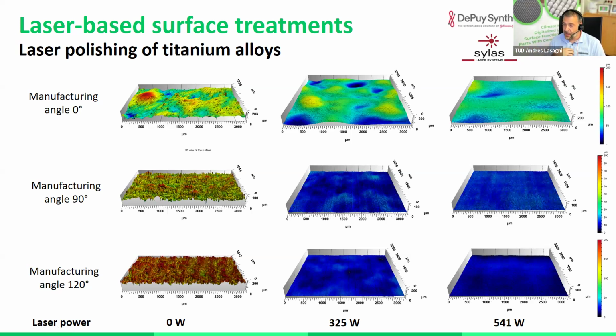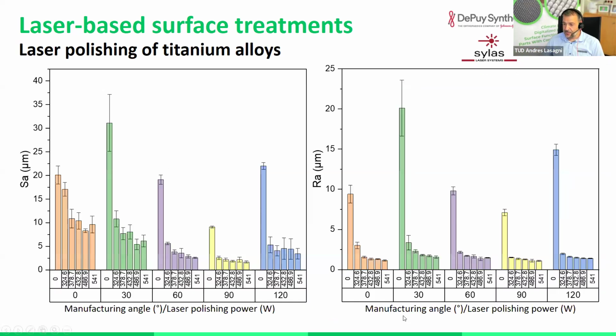We had also our micro roughness, and we can strongly reduce both of them. If we put some numbers to roughness values, here we are considering the surface values and from the profile, so the difference between Sa and Ra. So we look at the beginning here for the different manufacturing angles of 0, 30, 60, 90, 120 degrees. So we have roughness values over 20 micrometers. They're quite high roughness values.